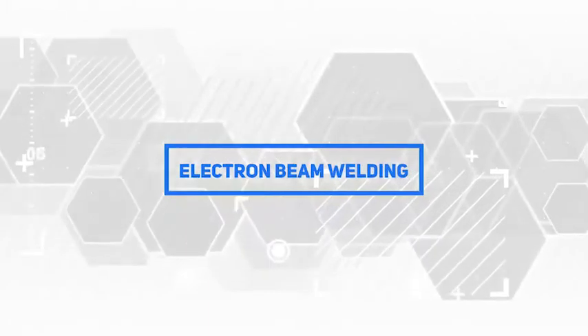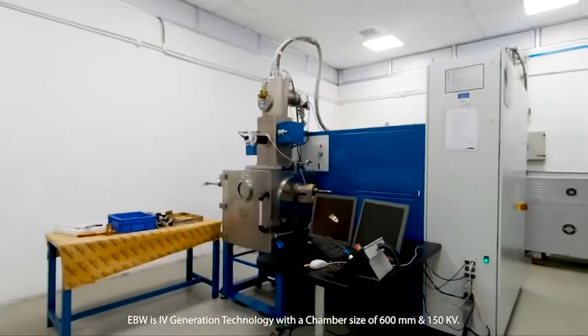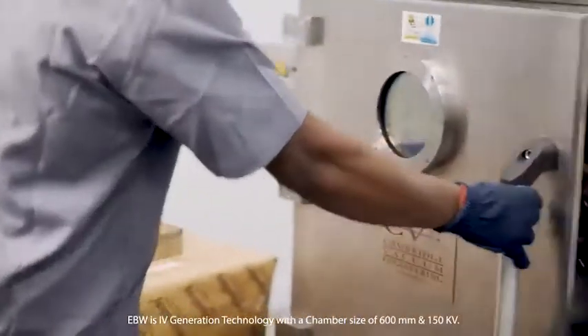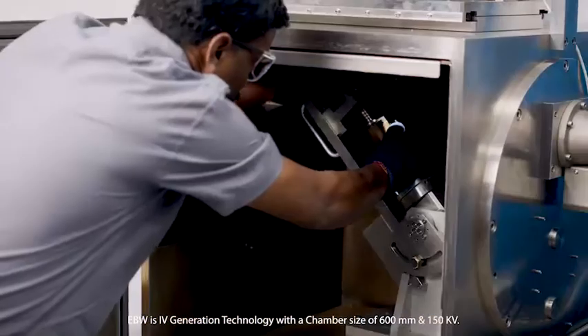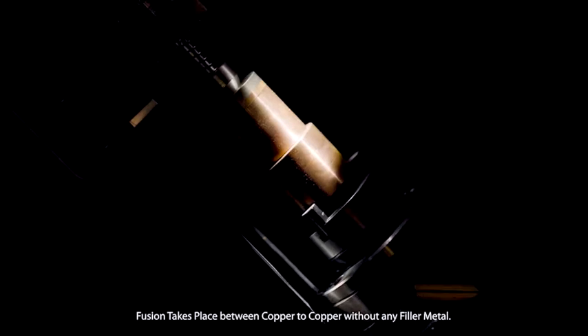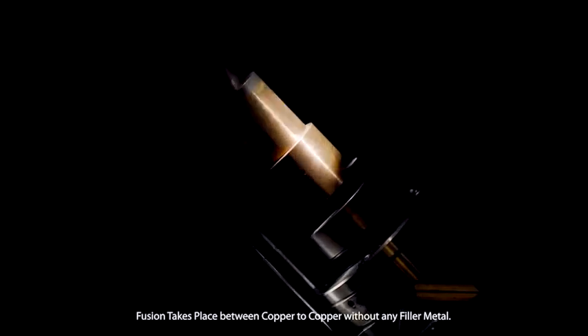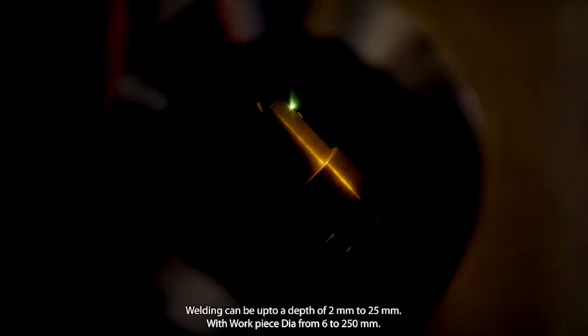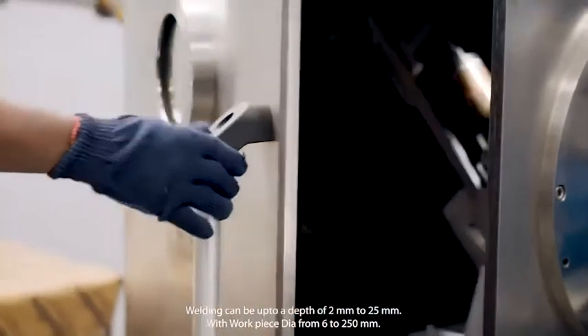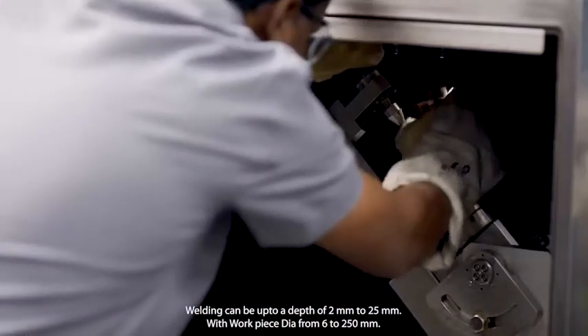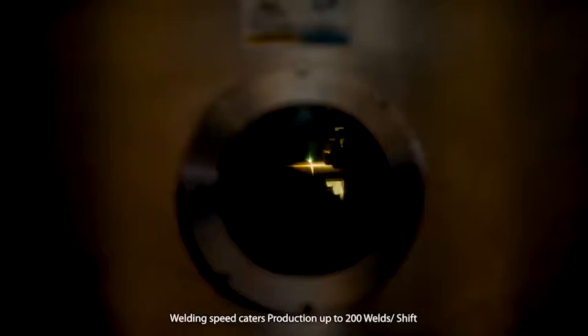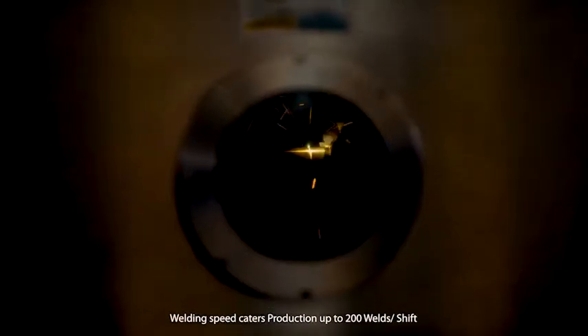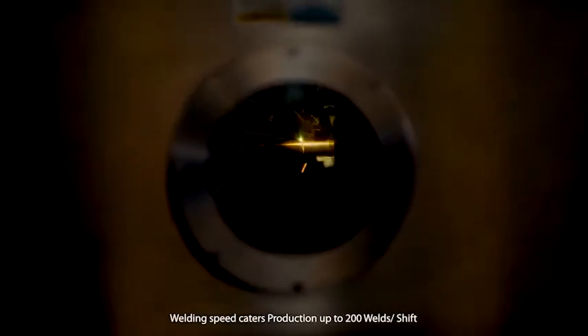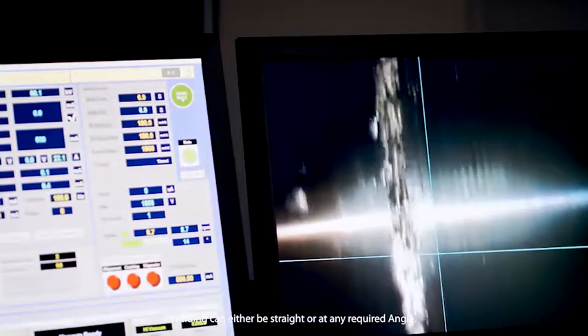Electron beam welding (EBW) is a fourth generation technology with a chamber size of 600 mm and 150 kV. Fusion takes place between copper to copper without any filler metal. Welding can be up to a depth of 2 mm to 25 mm with workpiece diameter from 6 to 250 mm. Welding speed caters production up to 200 welds per shift. Welding can either be straight or at any required angle.